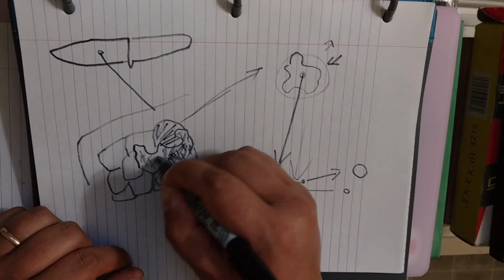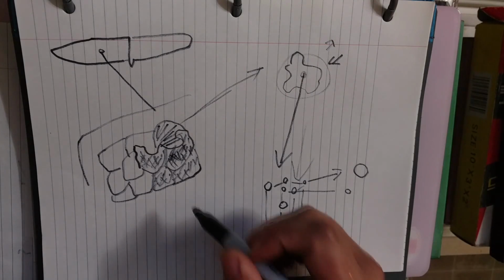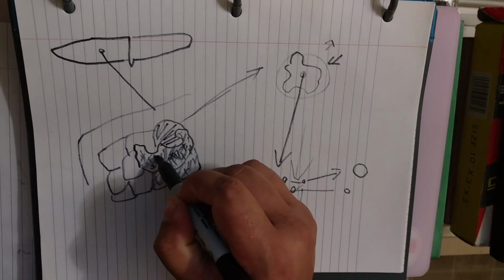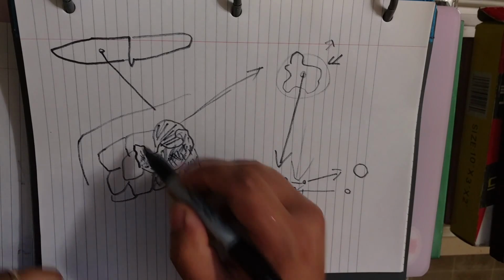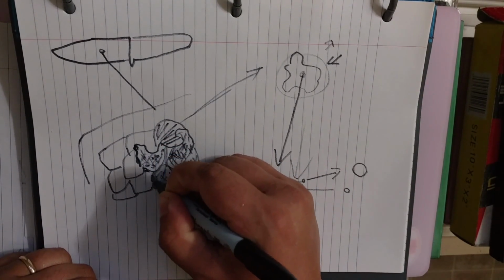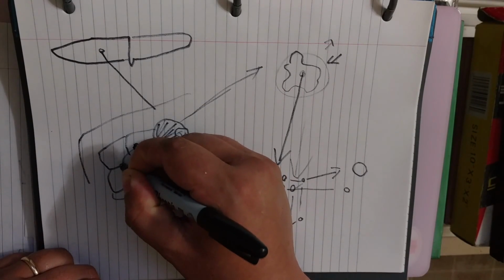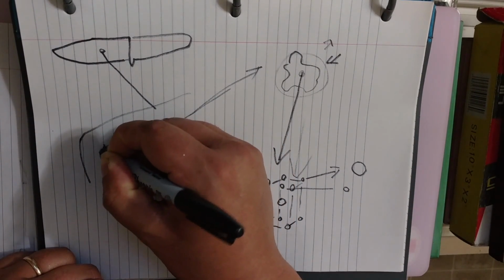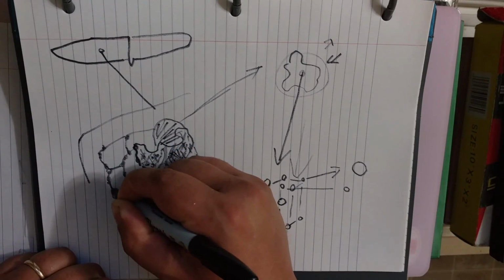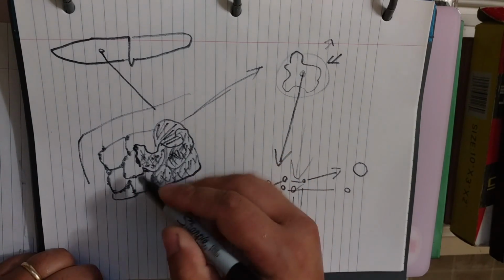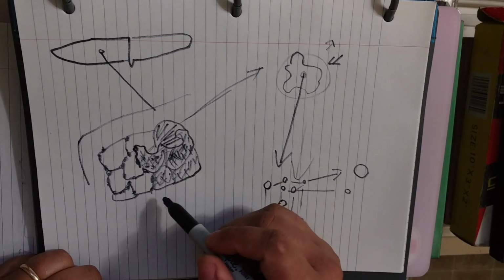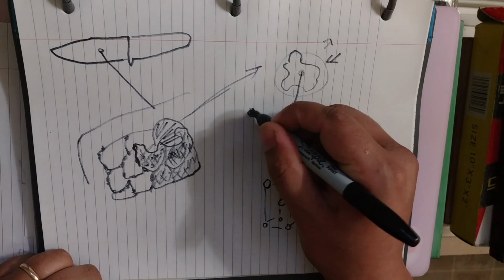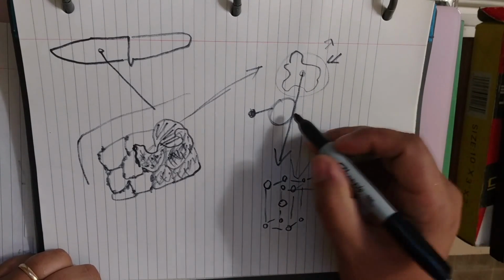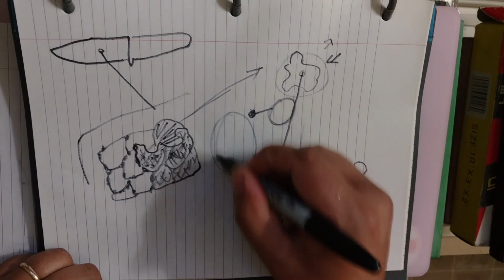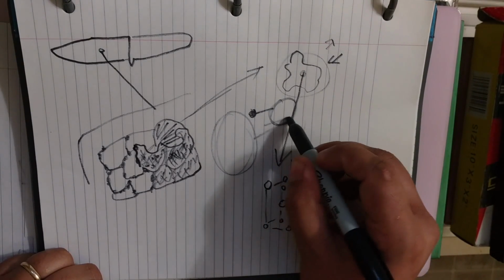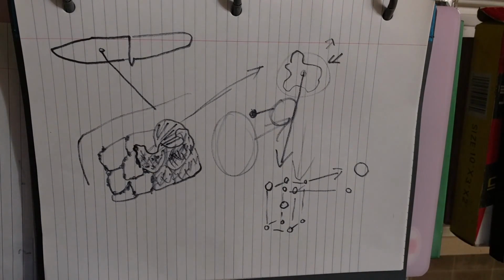And then what people also think of is what's called carbides. Some of those, the really fine ones, are dispersed throughout the Martensite, but a lot of them end up here at the grain boundary, especially when we talk about more alloyed steels that have other alloys like chromium. Then they start to take up spots at the actual grain boundary because they're just too large to move through the steel matrix. Something like carbon can diffuse really well because of its size relationship with the iron. It can move around a lot more, and something like chromium is a lot larger, so it can't really move through the iron matrix that well. But that's kind of it in a nutshell.